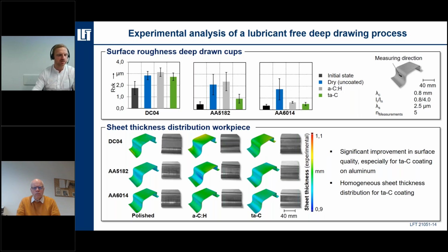To evaluate the impact on the resulting blank roughness in the next step, optical measurements have been performed. The test results reveal a significant improvement in surface quality, especially for the TAC coatings, which is the green one. Furthermore, a homogeneous sheet thickness distribution for the TAC coatings was gained, whereas the ACH coatings led to a higher necking of the parts, which can be seen here, for example.